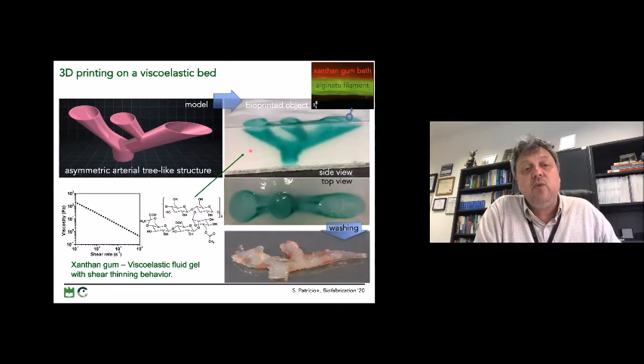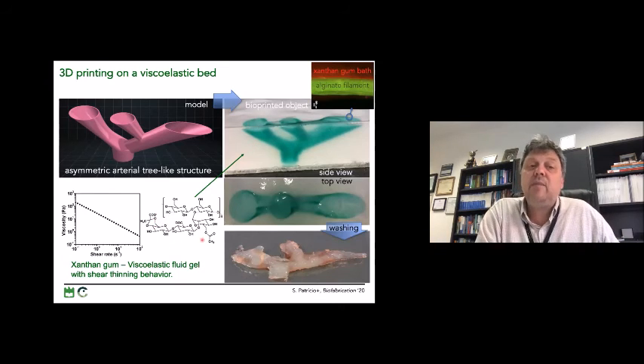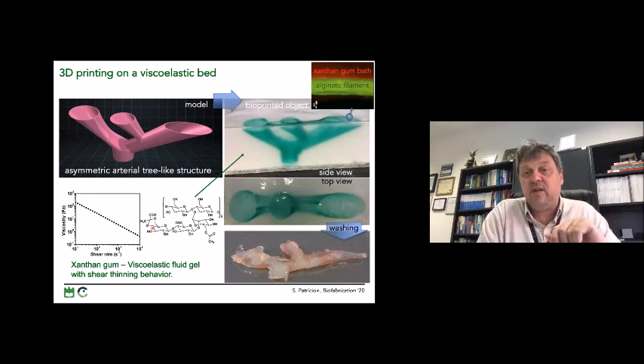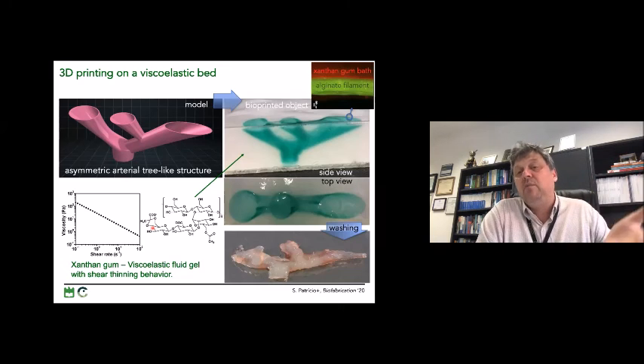The support bath that we use to process this kind of structures is made of a solution of xanthan gum, which is a polysaccharide. So this solution exhibits a shear thinning behavior. This property is very important for this case because it offers little resistance for the local extrusion of the bio-ink. So after the passing of the needle, that can go very easily because locally the viscosity will decrease, but after the passing, the viscosity will be restored to a higher value in the resting phase, allowing the fixation of the previously deposited extrudate.